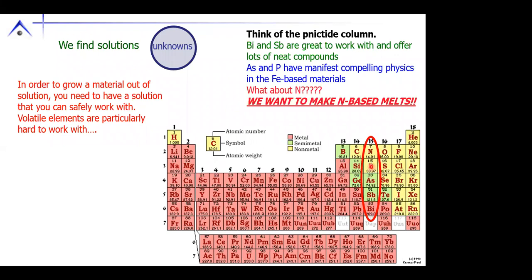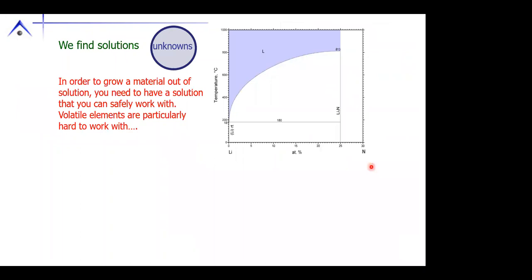Well, logically, the clever monkey would say, well, what about nitrogen? Can't we grow nitrogen materials? Well, one of the problems is it's hard to get nitrogen into solution, okay? So what we did was we looked at various binary phase diagrams. And there was this reported phase diagram for lithium and nitrogen that alleged you can have a liquid, at 600 or 800 Celsius that has nitrogen in it.